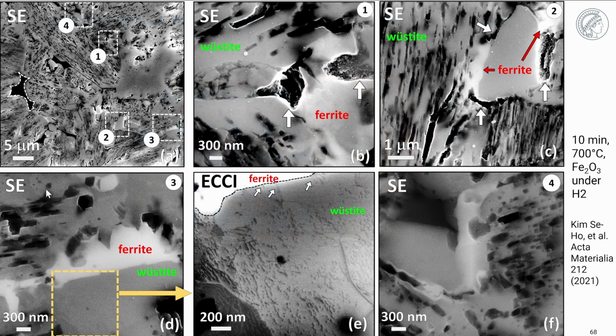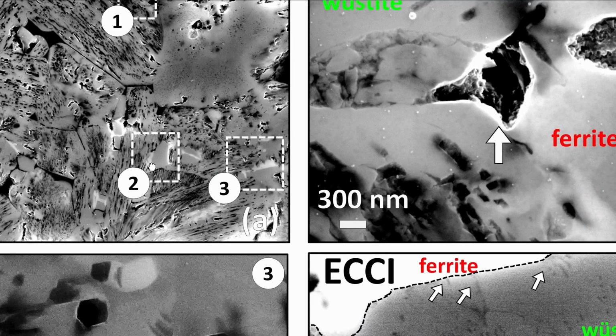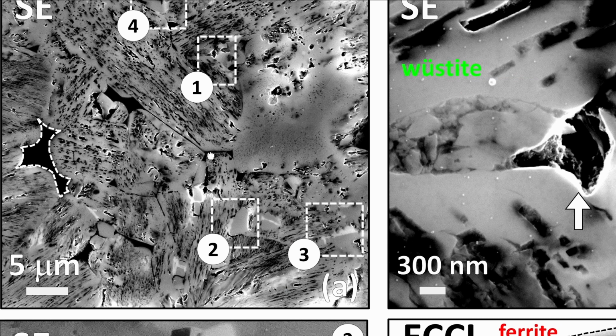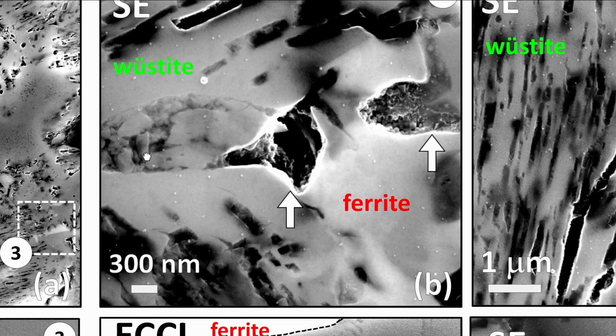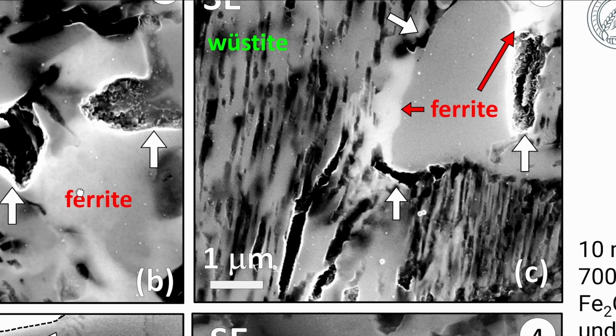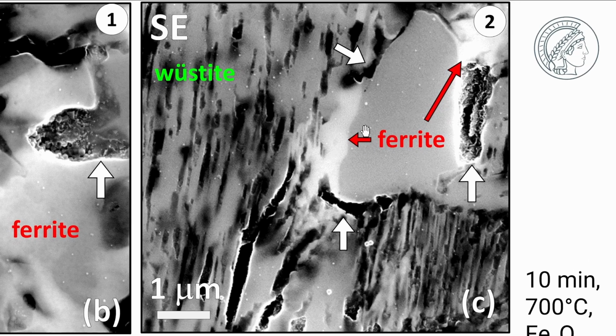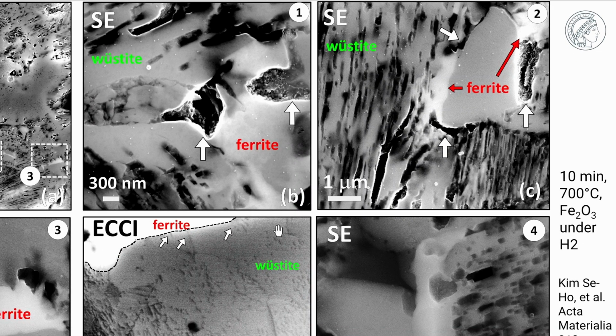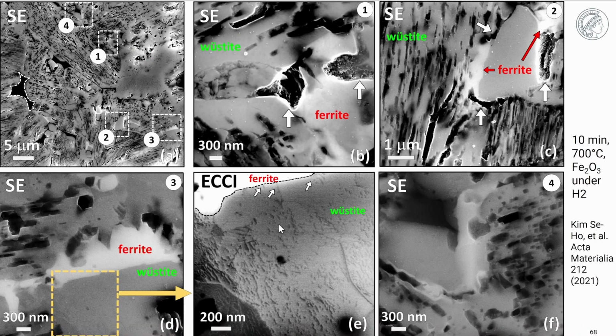However, when we really look into the microstructure, you see that things are much more complicated. You see here there are very different microstructure features that form. For instance, the ferrite with delamination that you see here. Here's the ferrite formed on the core region of wüstite, but you also see cracks, delamination, and very complicated substructure features. These are microstructures taken after 10 minutes at 700 degrees centigrade under hydrogen atmosphere.